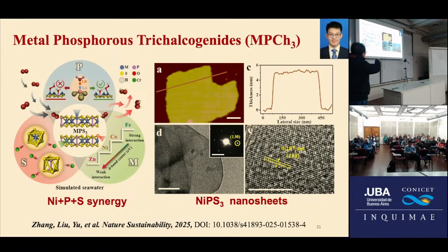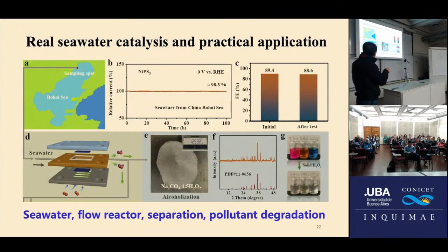Of course, we also did some deep engineering and identified nickel as the best metal center. And the phosphorus can contribute to the adsorption of water and promote the hydrogenation process towards both thermodynamically and kinetically favored hydrogen peroxide production. I don't have time to go into details here, so for details, you can go to this paper. We can use this material in real seawater for at least 100 hours. In simulated seawater, we can go to 1,000 hours.